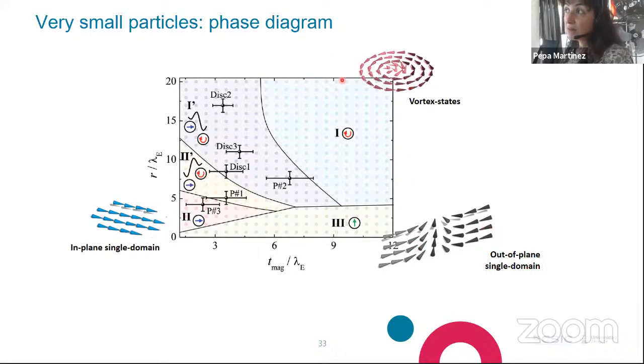For thinner particles with larger radius, that means, for instance, disks, you will expect to have a vortex state as the only possible stable state of the particle. For very small particles, you expect the typical in-plane single domain particle. So single domain particles. But what happens here in the border, in the frontier between these two regions?